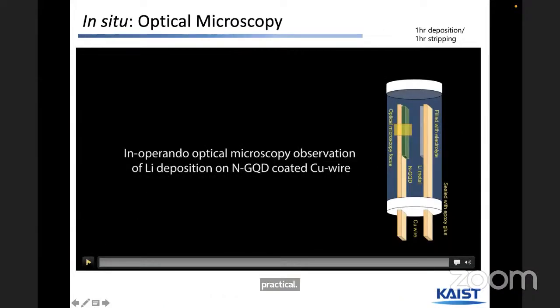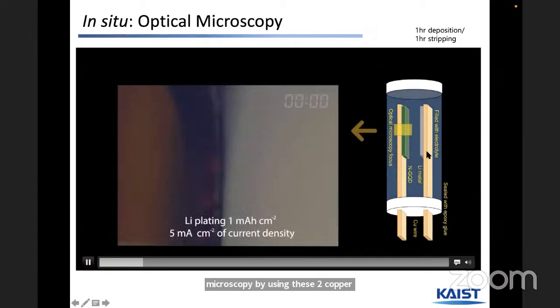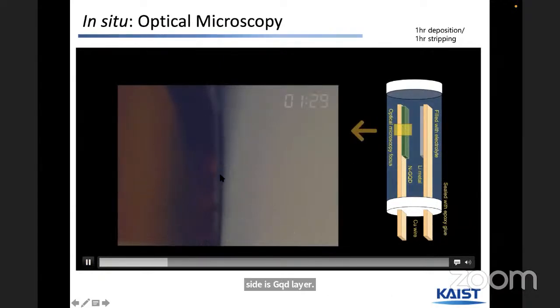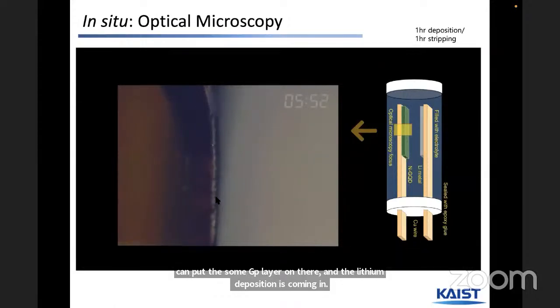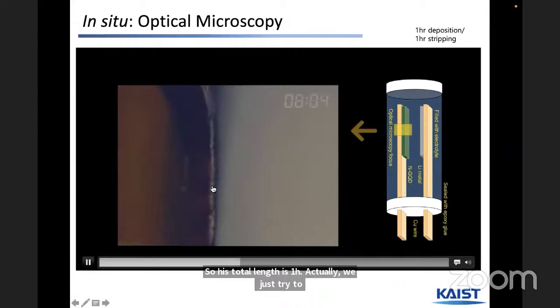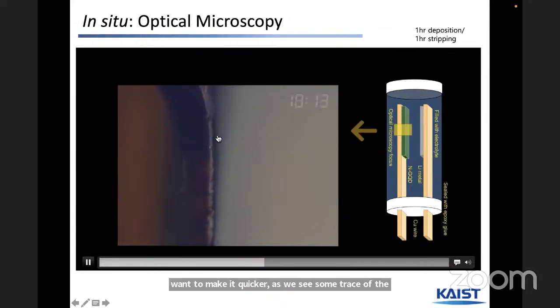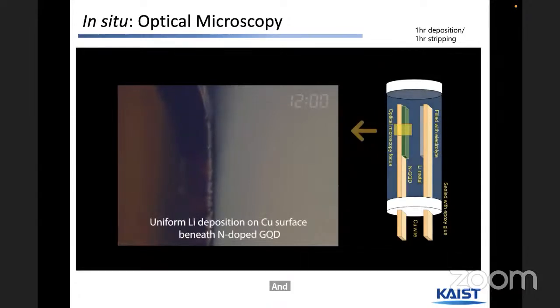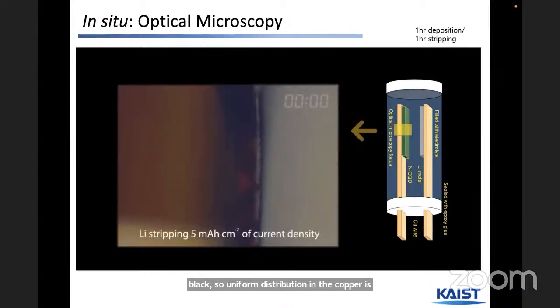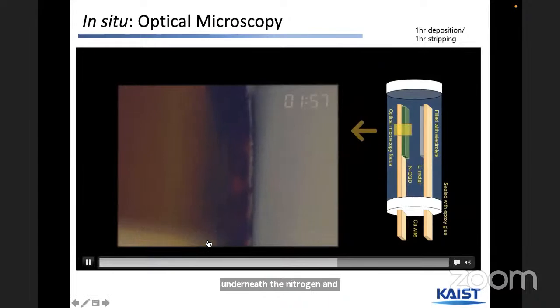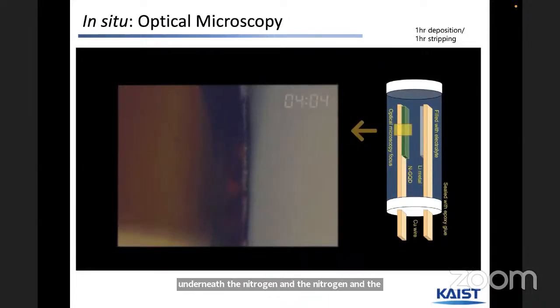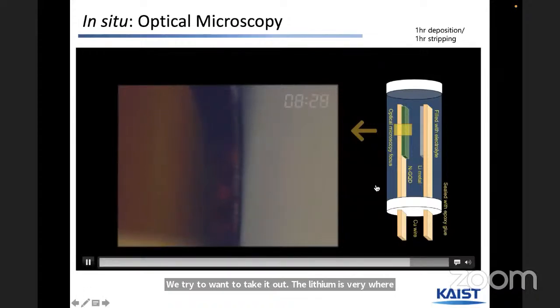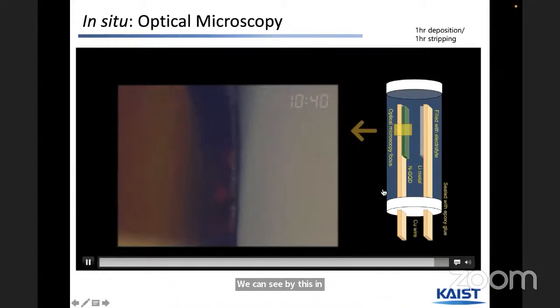Okay, finally, we'd like to show in situ operando optical microscopy using two copper electrodes. One side has the GQD layer, the other side is lithium. This is copper, we put some GQD layer on that, and the lithium deposition comes in. The total length is actually 1 hour, and we sped it up. As we see some traces of white lines, the farthest surface is still black. So there is uniform lithium deposition underneath the nitrogen-doped GQD layer on the copper, and the stripping is at a very high rate again, 5 milliampere per square centimeter. Reversible lithium operation has been observed, as we can see by this in situ operando optical microscopy.